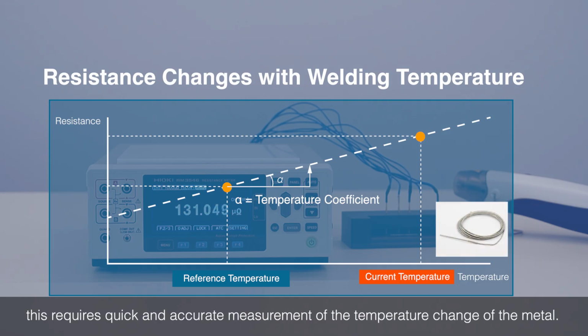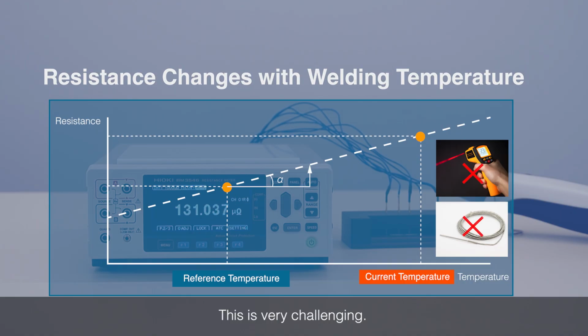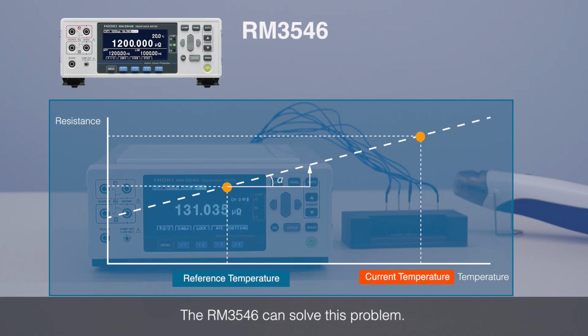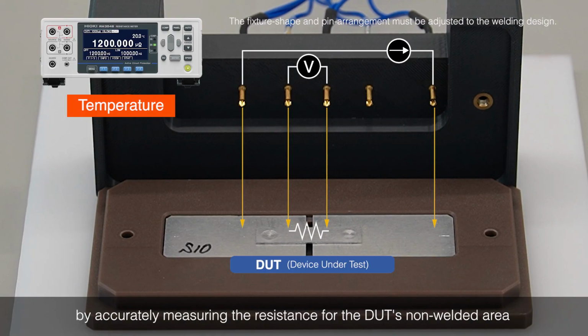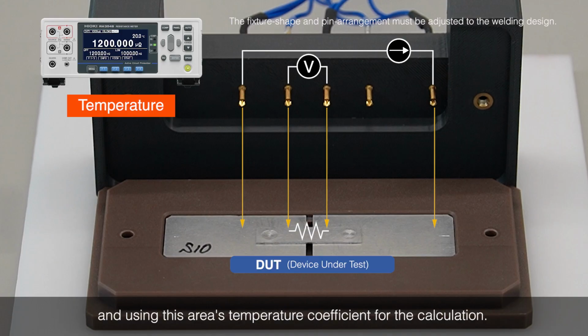However, this requires quick and accurate measurement of the temperature change of the metal. This is very challenging. The RM3546 can solve this problem. It can quickly calculate the DUT's temperature by accurately measuring the resistance for the DUT's non-welded area and using this area's temperature coefficient for the calculation.